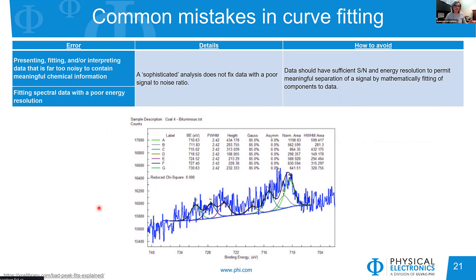Now, after showing a simple curve fit for reference spectra, let's look at some common mistakes. The first mistake concerns data quality. Curve fitting spectra with low signal-to-noise does not provide enough justification to perform the curve fit. You need high signal-to-noise and sufficient energy resolution to separate your spectrum into meaningful components assigned to chemical moieties. For elements present at very low detection limits, curve fitting may not be the appropriate way to process your data.